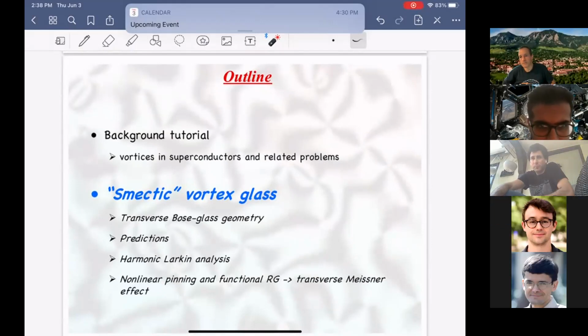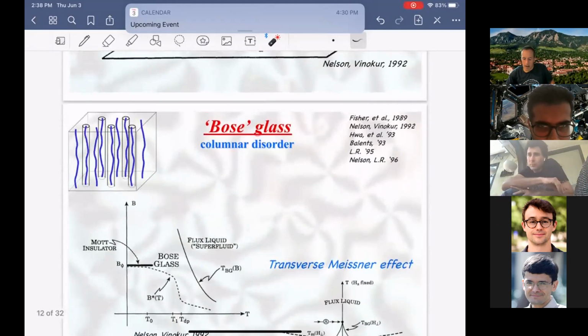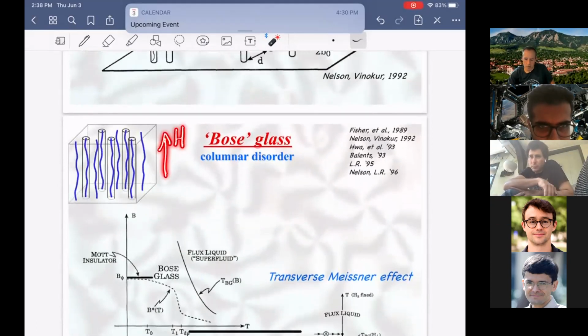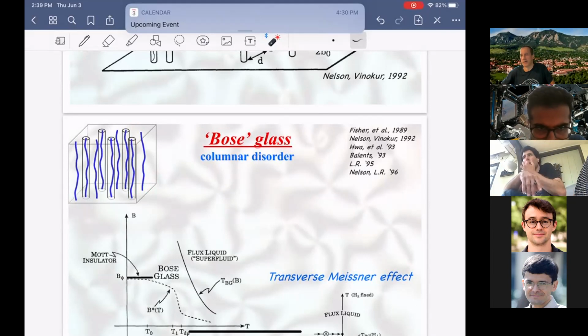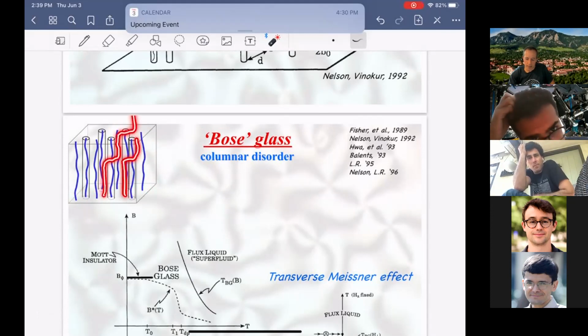Actually, Leo, could you remind me, why did the magnetic lines have to be vertical? Well, I apply an external field in this direction. But then I try to tilt it, so I apply a field in this direction. But that doesn't mean that the flux lines will follow that field. They might still prefer to follow the columns because they're pinned by the columns. Think of columns as holes in a superconductor. When you have holes, then a vortex line is also in a sense a hole in the superconducting order parameter. So you lower your energy if you continue following the columnar defects, the normal tracks, rather than tilting away. So there's a possibility of doing this, or there's a possibility of following the columnar defect and then hopping to another columnar defect. And this is something I will discuss.